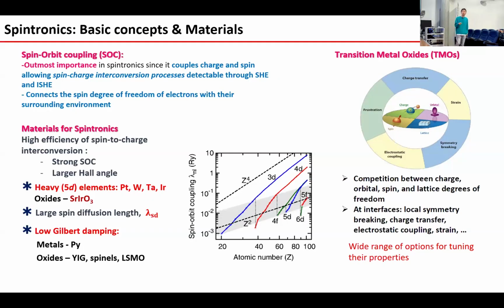So in our case, we need to achieve high efficiency of the spin to charge conversion. So we need both strong spin orbit coupling and a large Hall angle. The material choices are, for example, 5d heavy metal elements like platinum, tungsten, tantalum, and iridium.